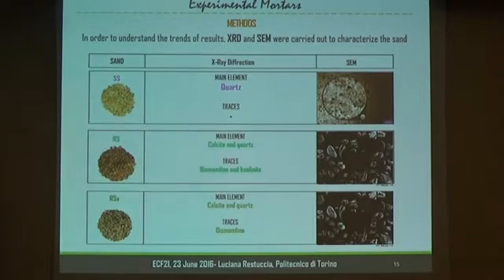In order to understand the trend of results, we decide to investigate the standard sand and the recycled sand by X-ray diffraction and scanning electron microscopy. By X-ray diffraction, we obtain that standard sand is obviously composed of quartz, while recycled sand and recycled washed sand present as main elements calcite and quartz, and the only difference between the two recycled sands, as you can see, is in the traces. In fact, recycled sand presents traces of gismondine and kaolinite, while in the recycled washed sand we obtain only traces of gismondine. So probably the washing process helps us to remove the finer and dirty fraction that is related to the kaolinite.